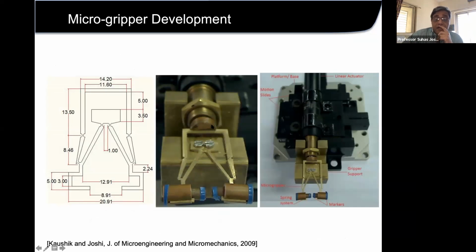If you apply a force here, then these grippers close. So if you apply a force from the backward end, the grippers actually close. Though this looks like a very elementary structure, it's a very interesting thing, because this whole gripper was manufactured, and then these two pipes were introduced. These are like small cardboard pipes. The whole gripper is not more than 50 millimeter by 20 millimeter. It's even smaller than that.